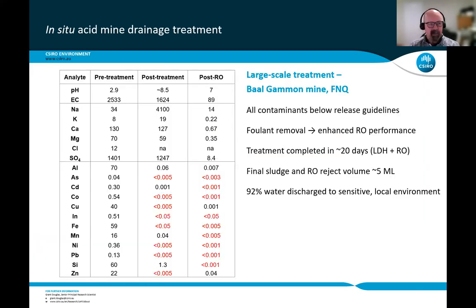Okay, so now if we look at the composition of the water pre-treatment, post-treatment and post-RO. Pre-treatment, pH was around 2.9, post-treatment about 8.5, and post-RO about 7. I won't go through every element, but if we look at the bottom box, we have things like Al, where we went from 70 to 0.06 after the layered double hydroxide treatment. Similar, very large reductions for all those in the red, which are all below detection limits. And we have silica as well, one of the major foulants, going from 60 milligrams per litre down to 1.3.